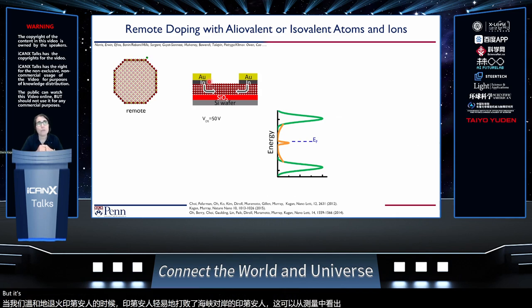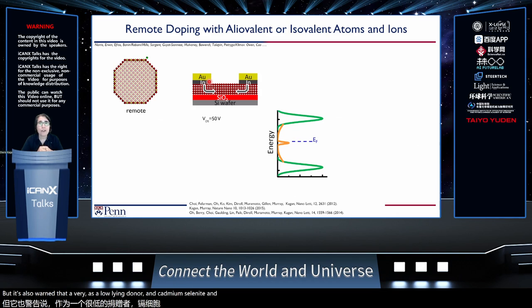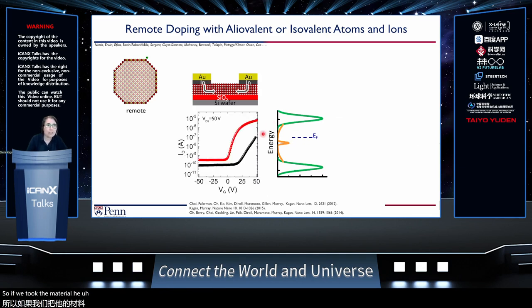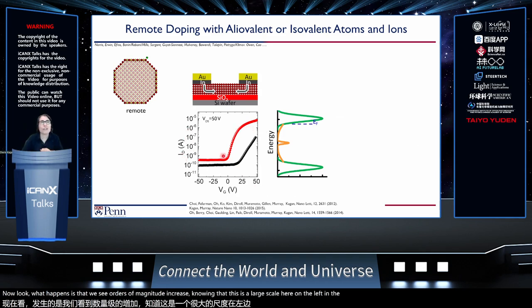But it's also a low-lying donor in cadmium selenide and very effective. Even if you look at the long history of literature in polycrystalline cadmium selenide, you'll see that it's really good at n-doping the material. So if we dope the material, now what happens is that we see orders of magnitude increase, knowing that this is a log scale here on the left, in the current that can be moved through the